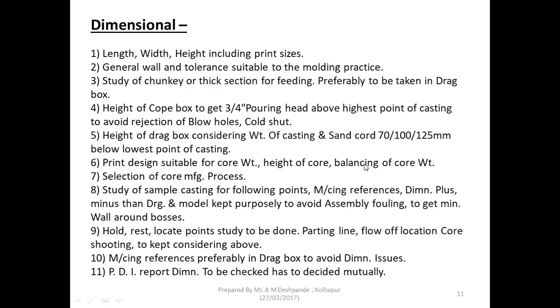And wall around the bosses. Simply, all the bosses are there. If you take at least 0.8 or 1 tolerance in molding and 0.5 machining, so total allowance variation will be around 1.5. If we do the drilling on the bosses, naturally the wall thickness will be less by at least 1 or 1.5. So that may create a problem. Hence, to get minimum wall around the bosses, the diameter of the boss has to be kept 1 or 1.5 plus. This is the most important point.